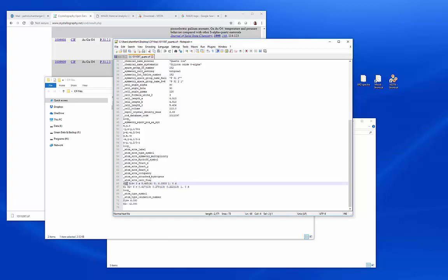I have silicon, and this one's named silicon 1, formerly with a plus 4 charge. 3A is the Wyckoff position that this silicon atom is sitting at. So 3 is the multiplicity, A is the Wyckoff symbol. Position in terms of fractional coordinates is given by these three numbers, 0.465, 0, and 0.33333. So that is the fractional coordinate position of the silicon atom.